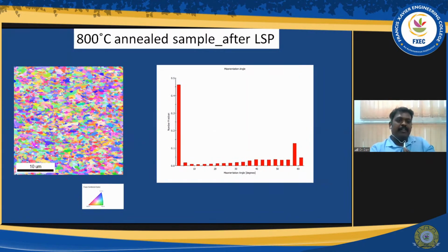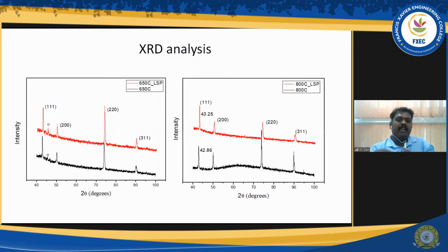After peening, my grain is refined to something around 345 nanometer, as you can clearly see here. After 800, the sample is refined to something around 600 nanometer. In the XRD, you can see precipitation, the sigma phase, here. Also, the majority of the peaks belong to FCC.